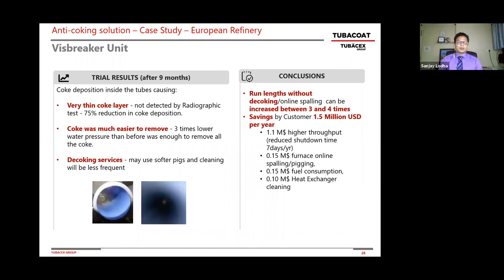So trial after 9 months, now it's been 14 months, but this was done at the 9 months. What we saw after 9 months is a very thin coke layer, not even detected by the radiographic test, and in essence, 75% reduction in the coke deposition. And whatever the coke that was there was very, very easy to remove, 3 times lower the water pressure. You can just put some water and it will come out.